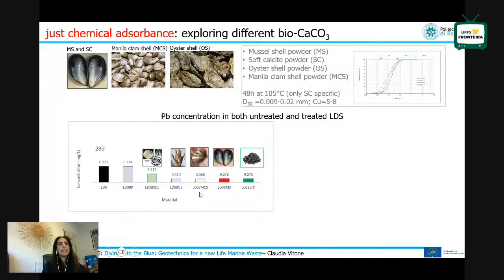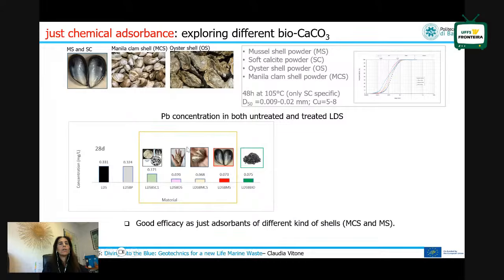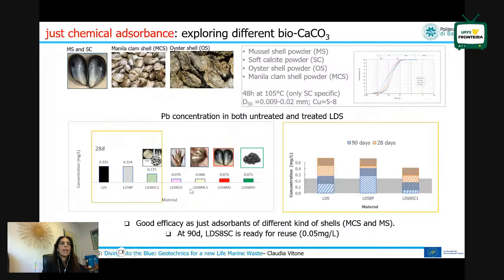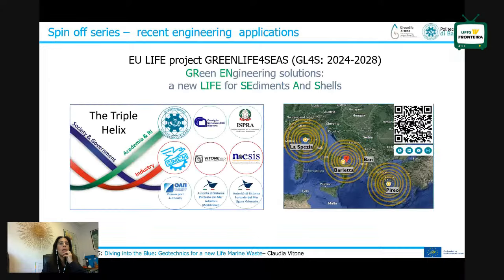And here you can see essentially what is going on if to the lead sediment we just add the shell powders. As you can see here, the concentration of lead is much reduced, so the shell powders are working very well. If we wait for longer curing times, up to 90 days, the soft calcite is lowering the concentration of lead to very, very low levels, so that essentially the material could be ready to be reused. This work is, of course, still ongoing.